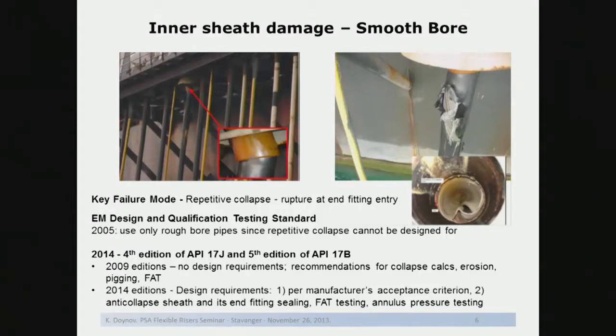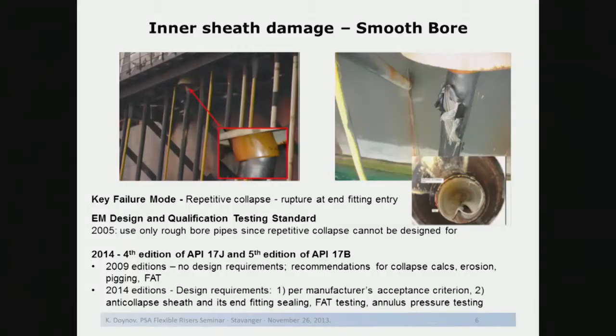The second example is of an inner sheath damage for a smoothbore water injection riser. What happened is that we accidentally lost an umbilical. Because of that, we had to frequently shut down a water injection riser with the sequence of closing a topside valve first, followed by the subsea valve. In that process, there was a vacuum being drawn in the hang-off point of the riser. So every time we drew vacuum, the inner sheath collapsed simply because of the differential from the atmospheric pressure. And after repetitive collapsing of that plastic sheath around the hard steel edge of the end fitting, eventually that sheath ruptured. So that's what you can see here.